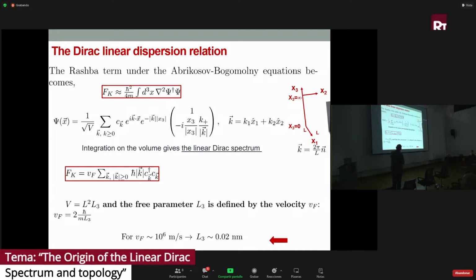The zero solution has a scale invariant parameter here, which essentially gives me a free parameter, and I will summarize all these parameters, including this mass, this L3, which is unknown, into the Fermi velocity, which is known to be 10 to the 6, and in fact, this free parameter is 0.02. So I cannot go into more details because of lack of time.